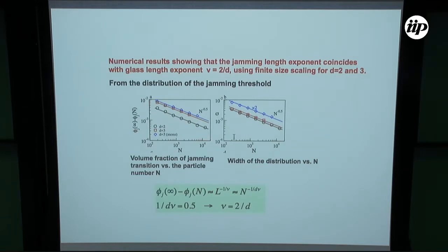So phi j of n is the jamming threshold for finite number of particles n. Phi j infinity is for n infinity. And this difference should scale as n to the minus 1 over d nu. And what we find is that for d equals 2 and d equals 3, we always get the same result, n to the minus 0.5. So if you put 1 over d nu equal to 0.5, you get nu equals 2 over d.